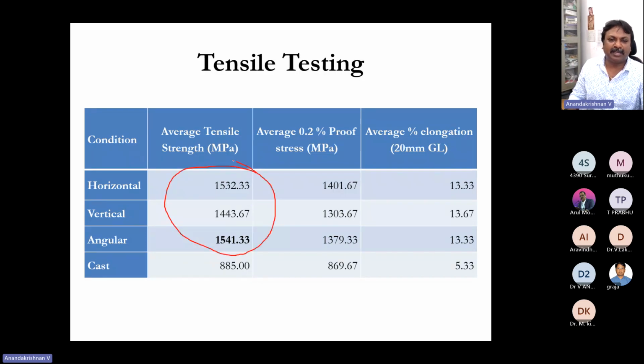You can see the tensile strength of the 3D printed components is almost twice that of the casting. Moreover, you can see the average percentage elongation is also very high, more than 2 times. So it's a highly recommendable process for which you can go for additive manufacturing.